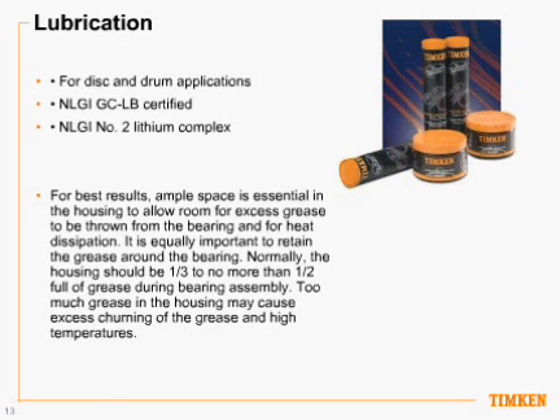Well, I suggest that you totally remove it, but that's due more to the contamination that was previously there or possibly there. As far as will they mix, as far as I know, the rating will tell you that yes, they will mix, but there are additives in the grease just similar to oil, and I can't swear that every brand will mix just because they meet these ratings. Okay, that's on the safe side. Yeah, err on the safe side and stick with one or the other, but don't mix the two. Absolutely.